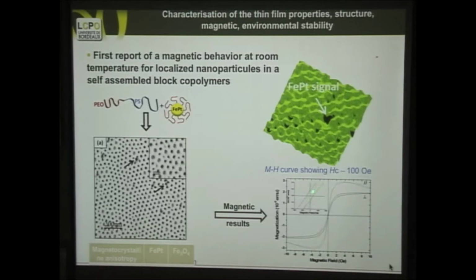Moreover, with this type of nanostructuration of the magnetic particles, we measured the remnant magnetization of these small particles at room temperature, which is approximately 100, and unfortunately the numbers don't appear here. Here we have approximately 50 compared to the iron oxide magnetic particle, which is 6. So you see, with this platinum iron, the magnetocrystalline anisotropy is very big for these small particles. So we have a good feature.